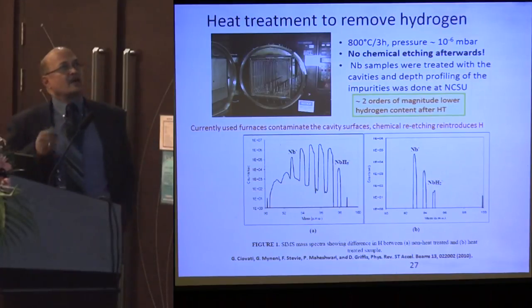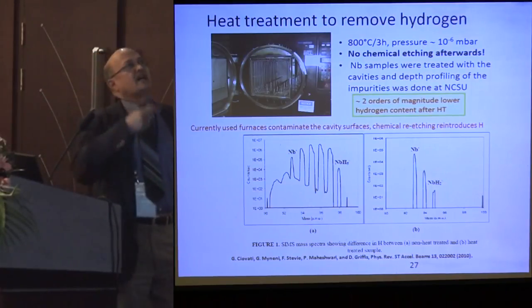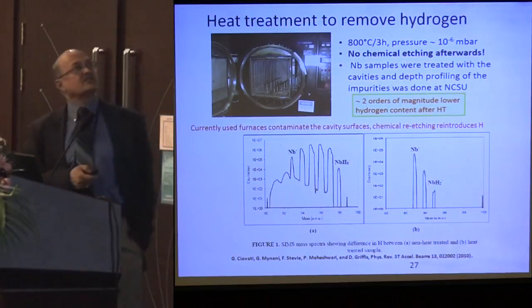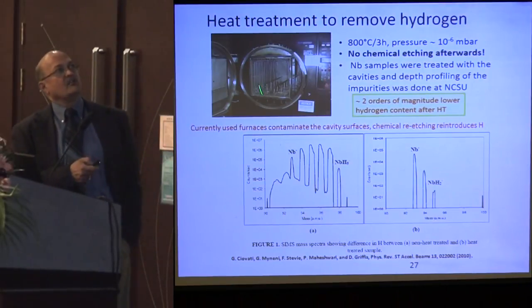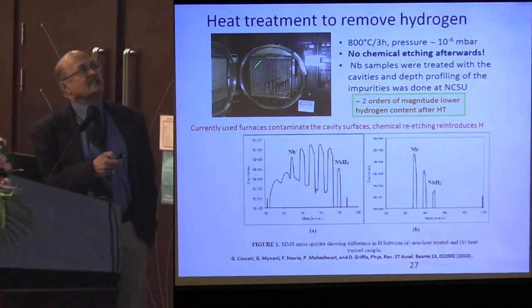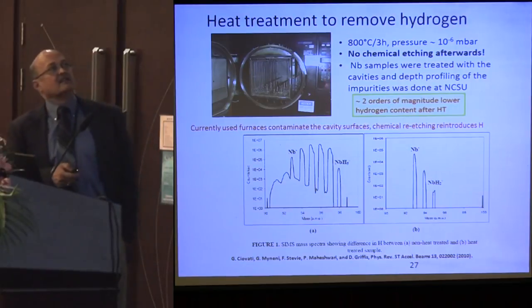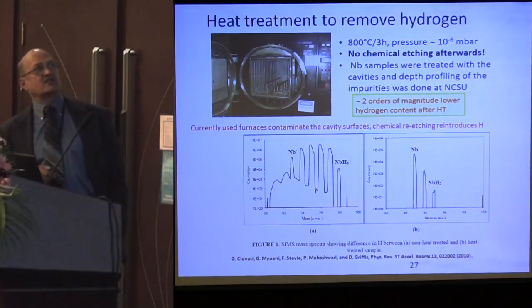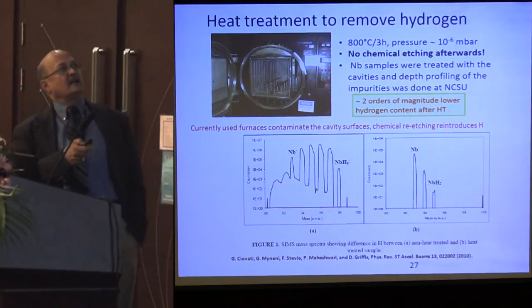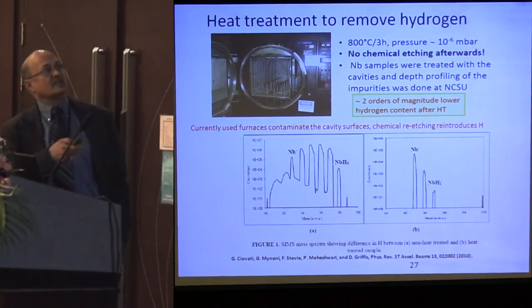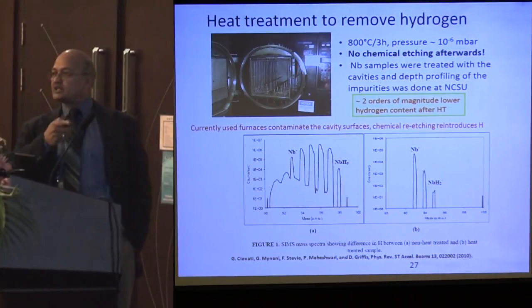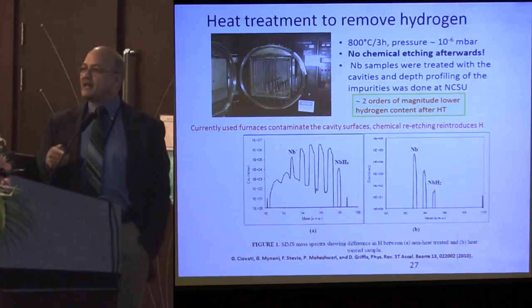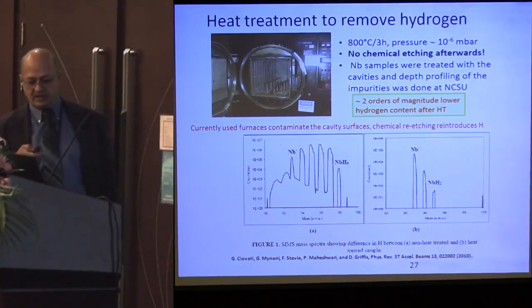The final step done is to remove this hydrogen. One degasses these cavities in ovens at around 800 to 900 degrees centigrade for about 3 to 6 hours. Since these furnaces are not very clean, you get surface contamination. As a result, you have to go back and do the chemistry on that to remove the surface. During this process, again, hydrogen goes back in. As a result, there is a problem associated with this.